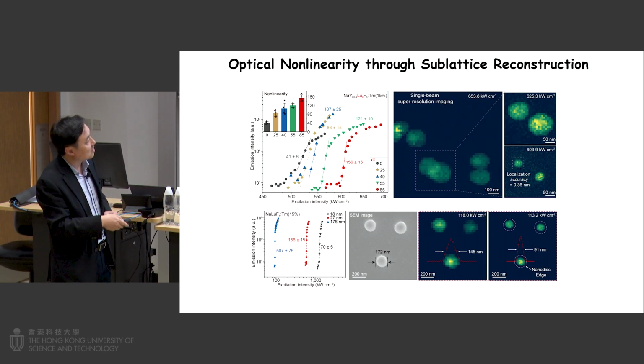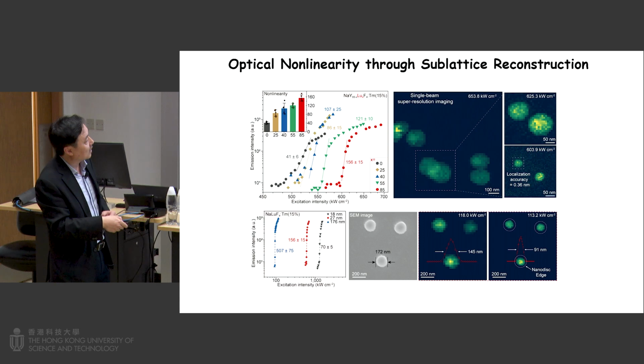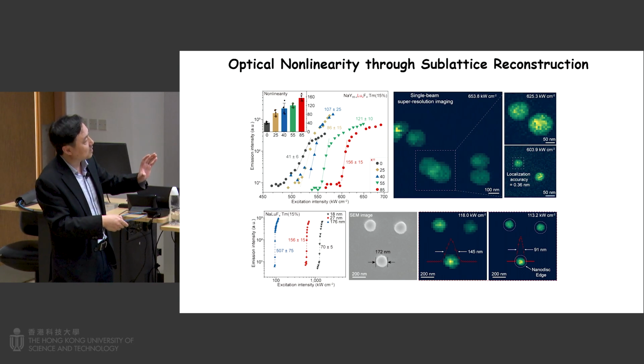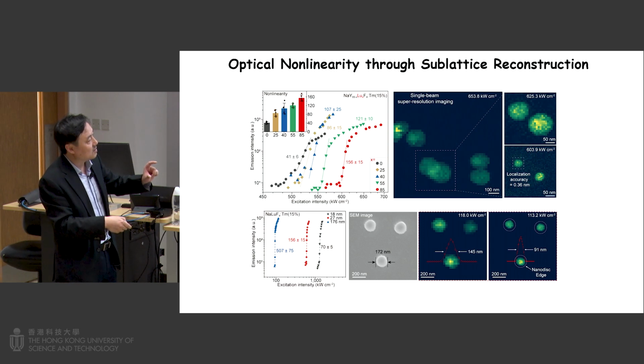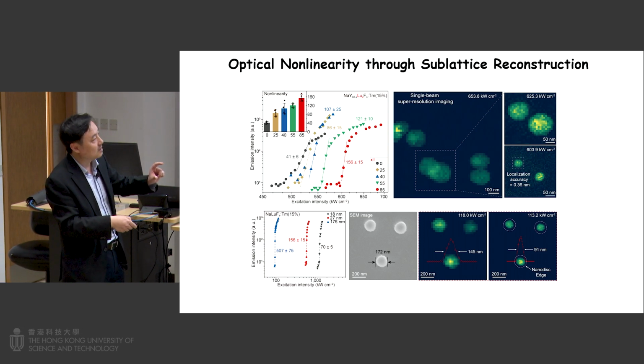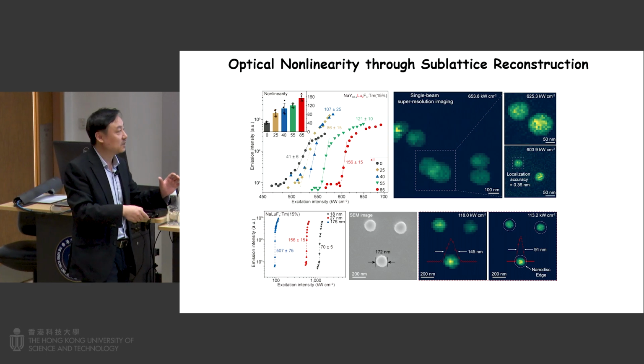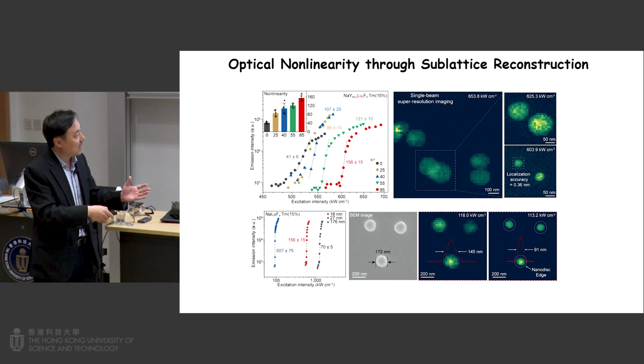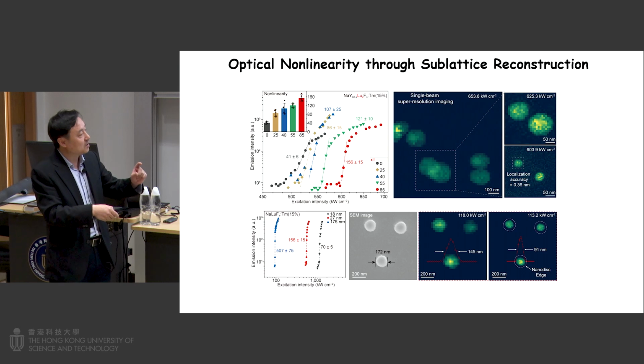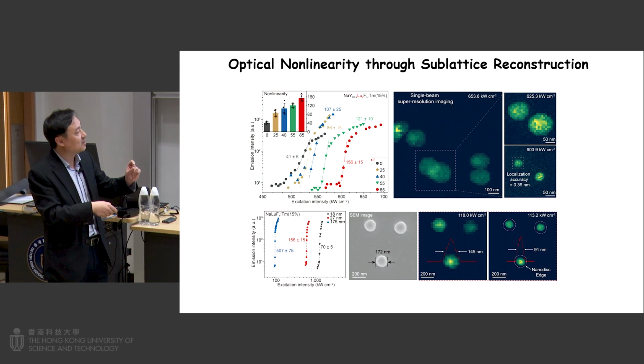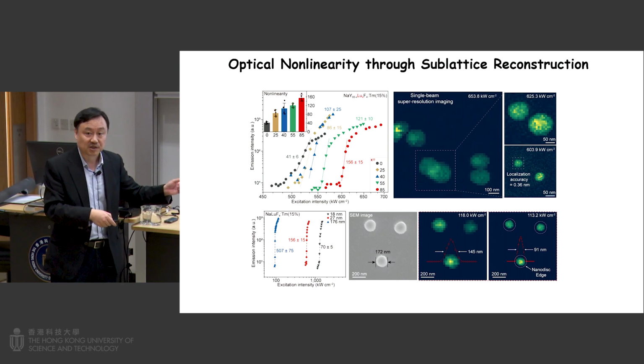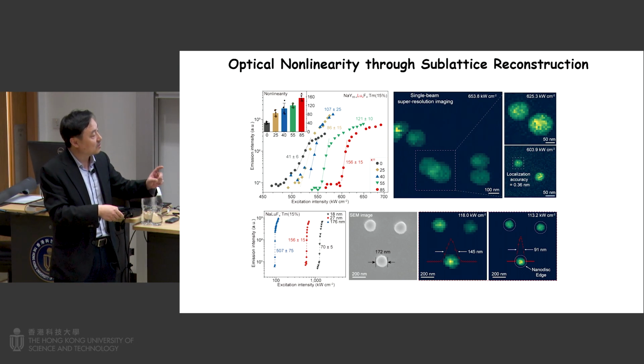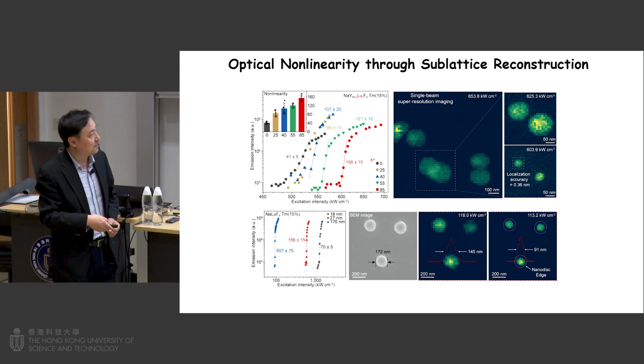We actually can use these designs to look at the particles. You compare the SEM image, you can see the particles are 172 nanometers, but our resolution here is very, very interesting, even 91 nanometers. This is beyond the physical size. This is very unique because in most cases, in optical imaging, the size you measure is typically larger than the real physical size. This phenomenon is all because we have high optical nonlinearity.